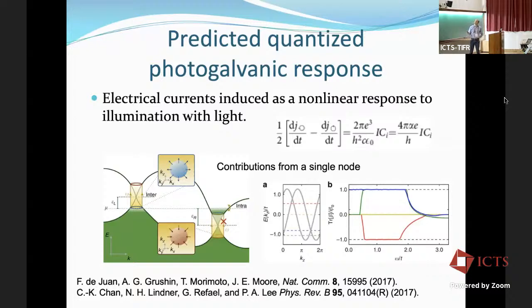So one thing that has drawn our attention in particular, and those that are interested in geometric responses, is that in this ideal situation where you have one Weyl node which is above the Fermi level and the other Weyl node which is buried below the Fermi level, which requires breaking of mirror symmetries and inversion symmetries to create this energy imbalance between the Weyl nodes, they must always come in pairs. So if you isolate the response to circularly polarized light from one Weyl node, you end up getting something which is proportional to the light intensity and the chiral charge of the Weyl node. And so this produces a quantized response in a second order response function. So Chern numbers is a first order response. There are fewer known second order responses that are quantized. And so in this ideal situation of just a single exposed Weyl point, you get this quantized response.